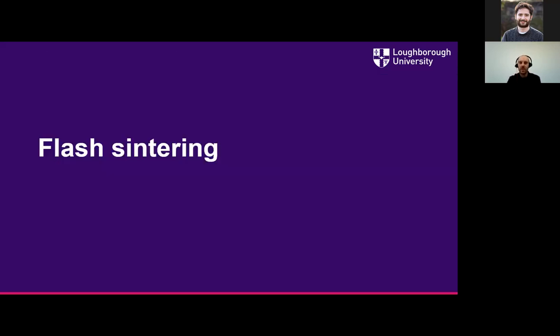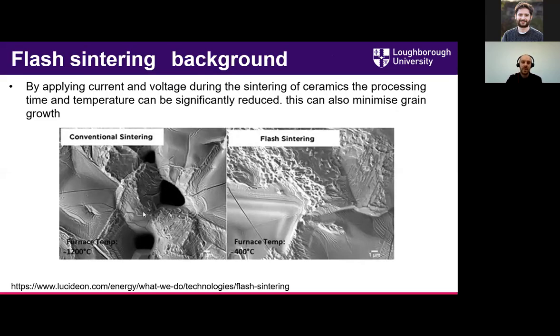So next, I thought we'd talk about flash sintering, just touch on that. For ceramics, if we'd like to sinter them, one of the ways we can sinter them at low temperature is by applying a current to them. In a conventional sintering of something like zinc oxide, we would sinter it at 1,200 degrees, maybe for an hour or so. Whereas with flash sintering, we can just take the furnace up to 400 or 600 degrees, apply a current, and cause what's called a flash to occur.